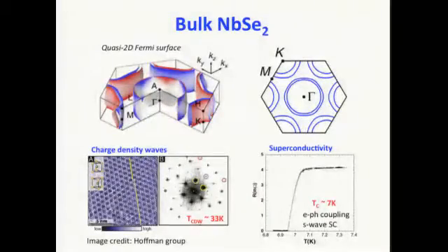And the material is somewhat interesting, with two instabilities in the Fermi surface. The first one is when you cool down the material below 33 Kelvin, it turns into a charge density wave, meaning that there's an extra periodic modulation of the charge carrier density below this temperature. And this is the STM image from the Hoffman group. And when you further cool down the sample below 7 Kelvin, it turns into a superconductor with zero resistance. And so far, we believe the superconductivity is driven by electron-phonon coupling. It's an isotropic s-wave superconductor.